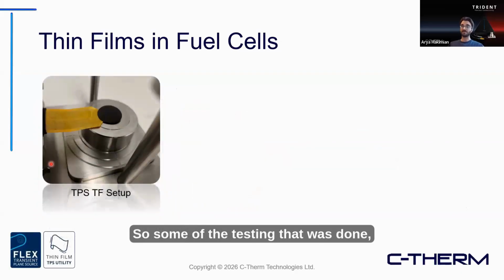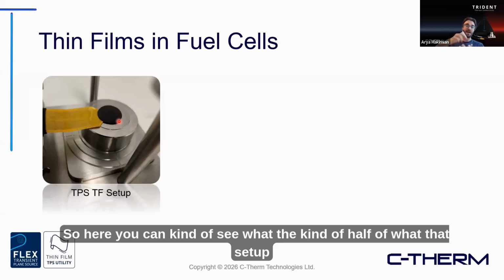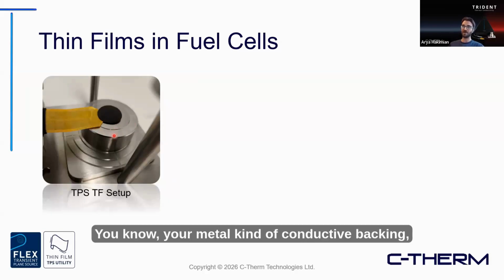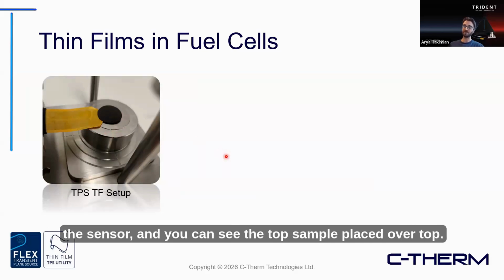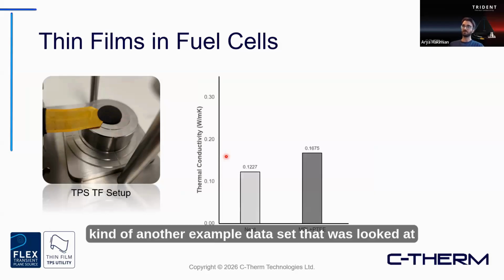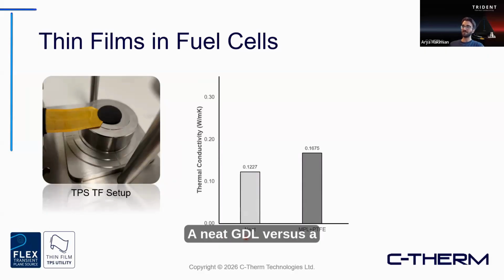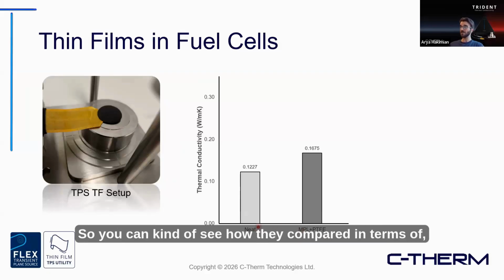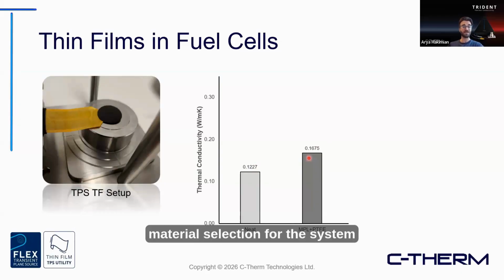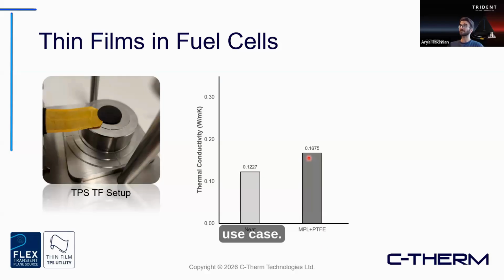So some of the testing that was done, again, using the TPS thin film setup. Here you can see about half of what that setup looks like: your metal conductive backing, the sensor, and you can see the top sample placed over top. Here is another example data set that was looked at, comparing two different materials, a neat GDL versus an MPL plus PTFE sample. So you can see how they compared in terms of material selection for the system use case.